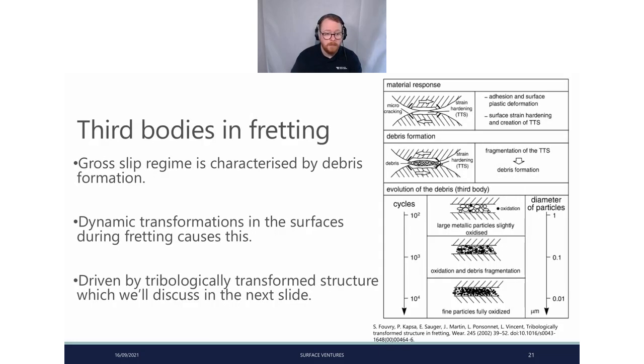or as much as is feasible to instrument. So I talked a little bit about third bodies in fretting. So gross slip, our sort of highest amplitude fretting regime, is characterized by debris formation. So this is where these sort of synergies really come into effect. Abrasion of the surface, adhesion between the surfaces, and plastic deformation between them is going to generate wear debris. We can get strain hardening right on the contact points, micro cracks forming around them, and this can tribologically transform the structure, so generate wear debris.